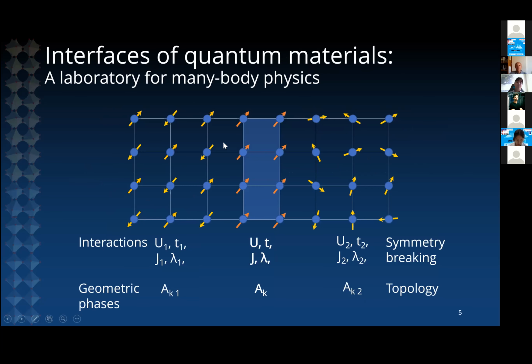And to visualize a little bit what type of studies we perform, essentially we synthesize atomically sharp interfaces between material A and material B. So the two materials are characterized by quantum mechanical interactions, such as the on-site Coulomb repulsion, hopping integrals, magnetic interaction, spin-phonon coupling. And then they're also characterized by topological properties arising from their geometric phases. And then by creating sharp interfaces, we achieve a certain degree of control over these various parameters, and essentially create a laboratory for many-body physics, where sometimes we can induce the formation of two-dimensional electron systems with tunable interactions.